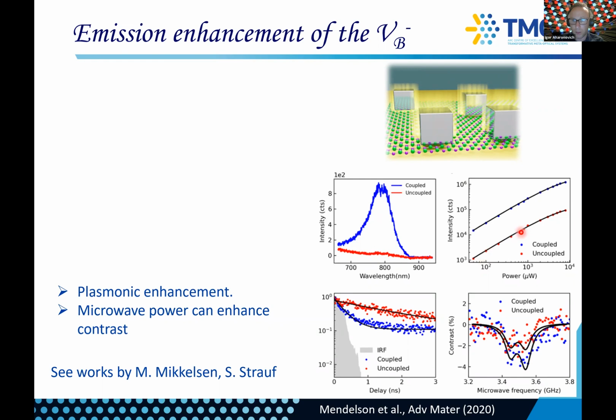And this is the power plot. You can see that there is a lot of enhancement. But again, unfortunately, we have not measured any single photon emission from this defect. The ODMR contrast gets a little bit better.